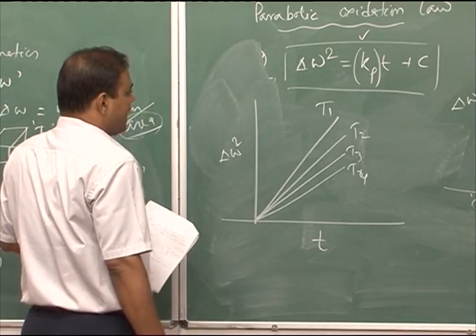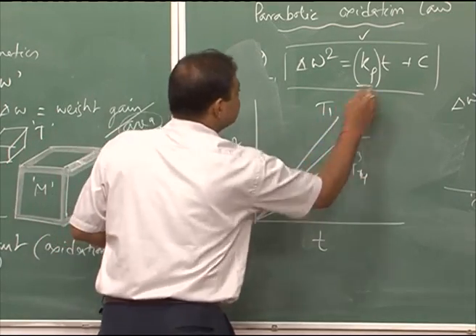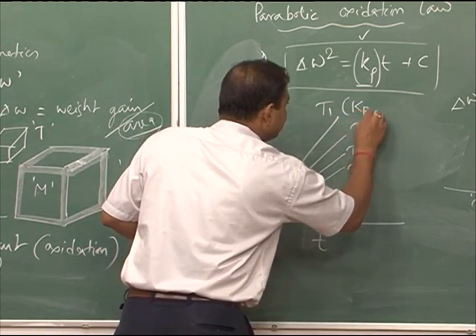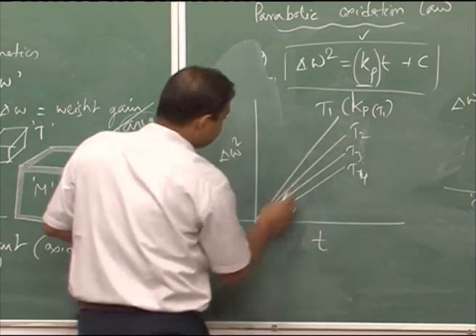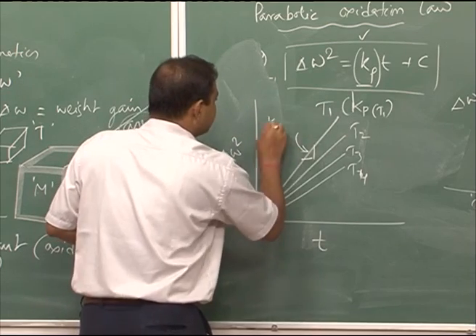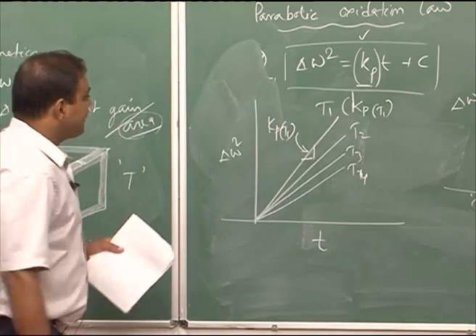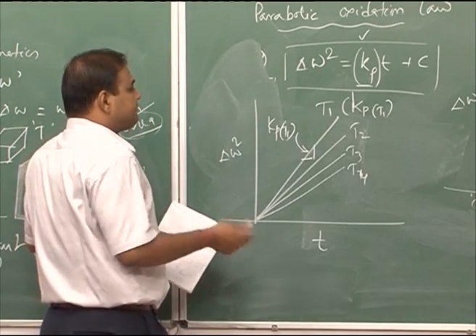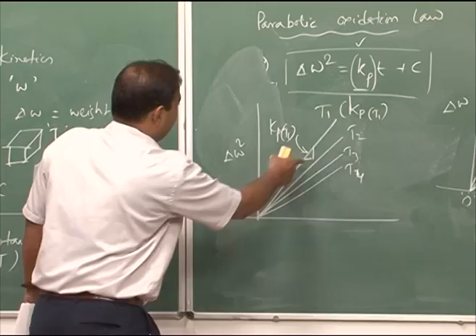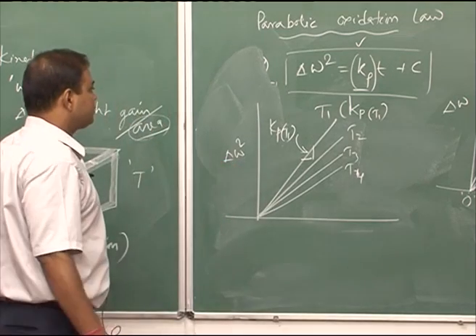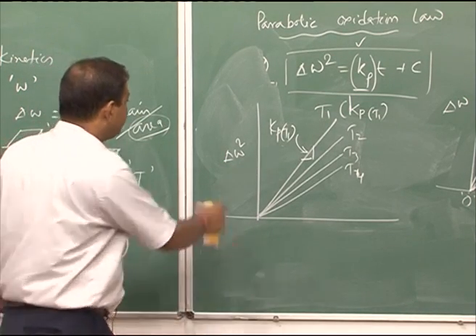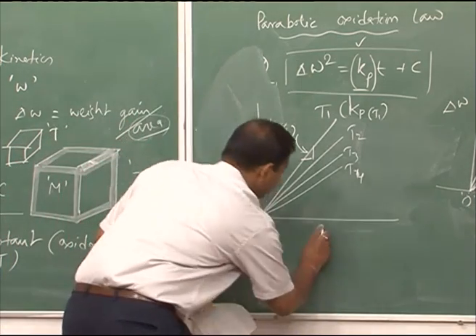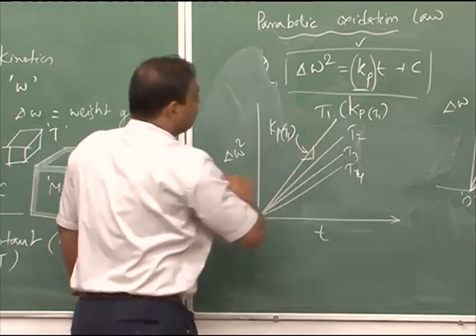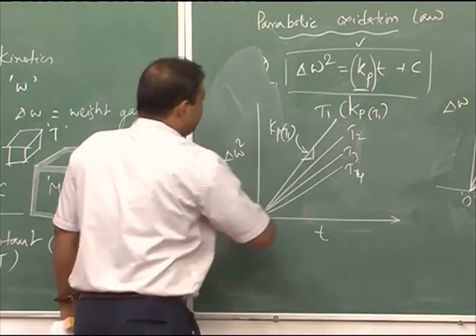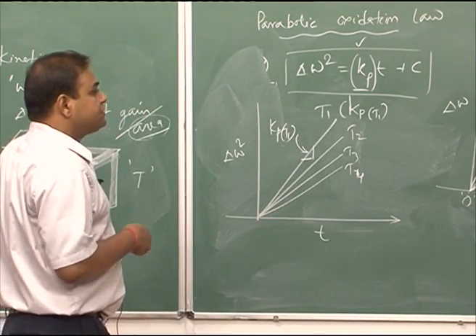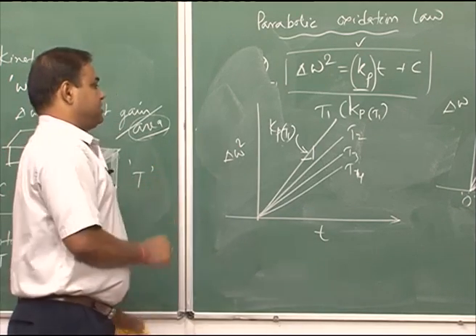Now, once we have all the straight lines, I can calculate the value of Kp at that temperature. So, this is Kp at T1, which is basically the slope of the line. This slope would give you the Kp at temperature T1. Like that, we can find out the other rate constants at other temperatures. So, at different temperatures we can find the Kp value, the parabolic rate constant for the oxidation process, if we plot del W square as a function of time. Then we get all the 4 Kp values, and these 4 Kp values enable us to find the activation energy for the oxidation process.